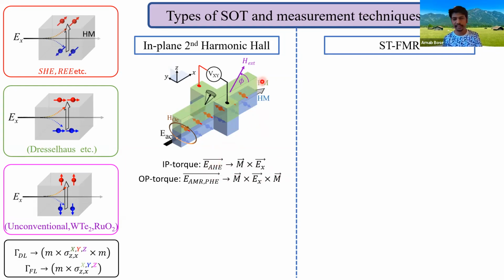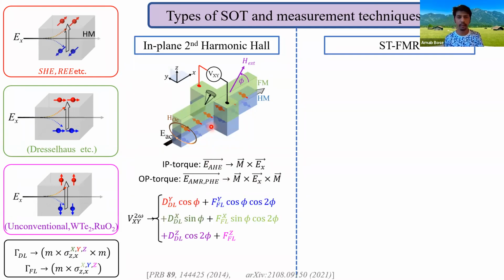Now we have oscillatory resistance and oscillatory current, and both mix up to produce the second harmonic Hall voltage that we experimentally observe or measure, which will have a particular angular dependence with respect to the magnetic field that we apply or that we rotate. For example, if we have damping-like torques from the spin Hall effect, then it will have angular dependence of cos phi.